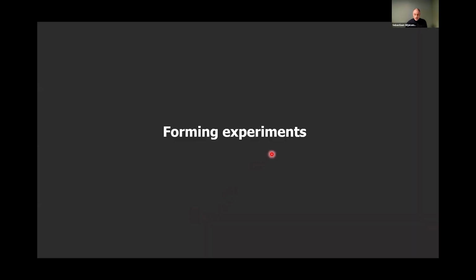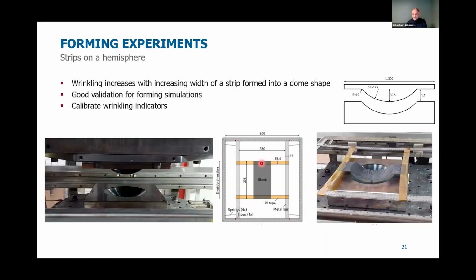Now, another small tool or method that we developed over the last years in terms of forming experiments is this hemisphere or dome that Sebastiaan also showed in his presentation. He demonstrated all the wrinkles that occur, for example, with quasi-isotropic laminates if you try to mold the full dome. We found out that if you stamp form strips with various widths, you can see at which width for a certain layup the first wrinkles occur. And if you then simulate all these measurements, you can really validate your simulations. You can also start calibrating your wrinkling indicators here.